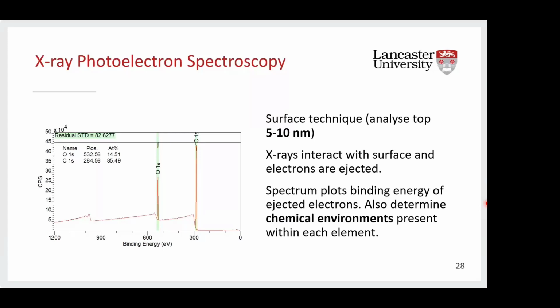Now, I have mentioned that varying the plasma parameters is going to influence the coating properties, but before I expand on this, I'm just briefly going to explain the primary analytical technique that we use to evaluate these coatings, and this is X-ray photoelectron spectroscopy. And we're lucky enough to have an XPS spectrometer available in the physics department at Lancaster. XPS is a surface technique, so it's sensitive to the top 5 to 10 nanometers of your material, and it's used to quantify the elements on that surface and evaluate chemical state information.